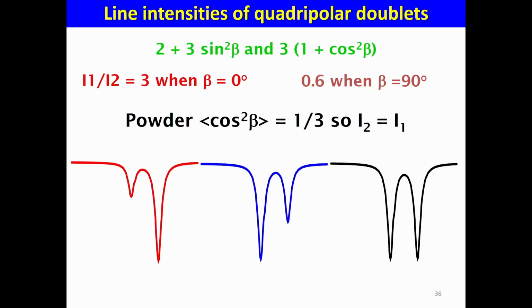But in some cases, you can see that the powder is not homogeneous. Because when the powder is well random, you have a pure doublet and the intensities are the same. And sometimes you will see some asymmetry. So starts the problem. Where does this asymmetry come from? Sometimes you have some samples, for example, in some clays. I would give another example. If you want to put some coins on a table, it's difficult to have a random distribution of all coins. So you will prefer some direction.